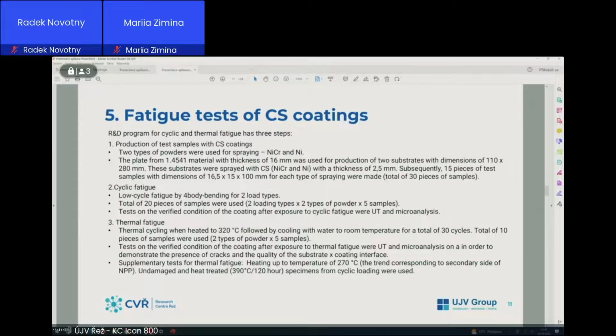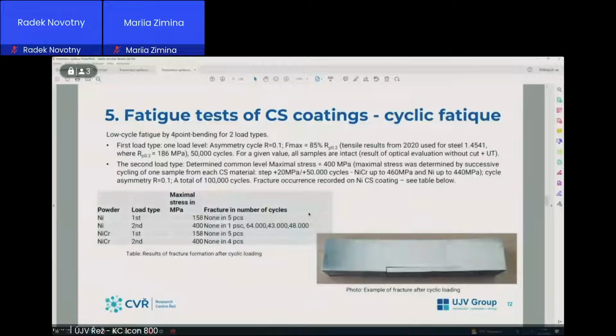And because from the low cycle fatigue we had not damaged samples, we made a decision with CHESS to perform supplementary tests for thermal fatigue, which would correspond to the secondary side of nuclear power plant Temelín. And in this case, we performed 10 cycles. Here are results.